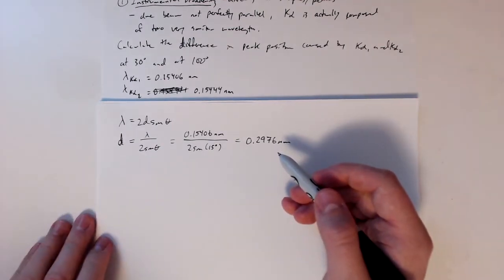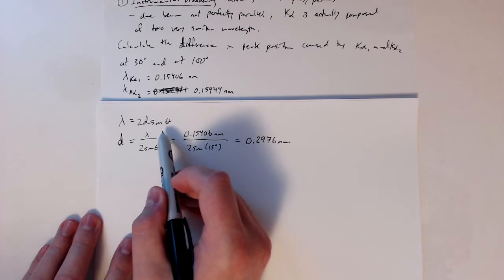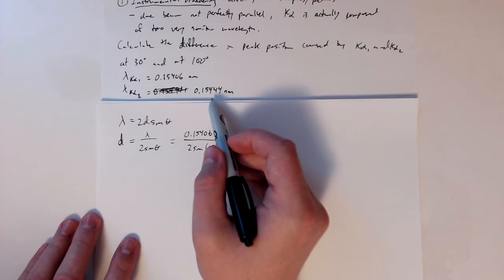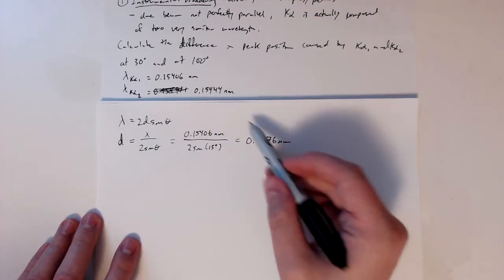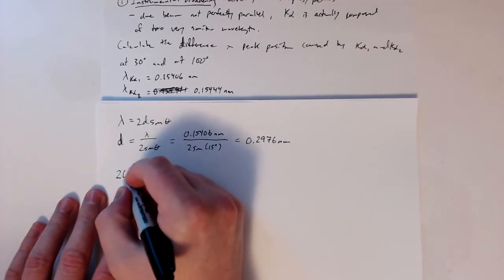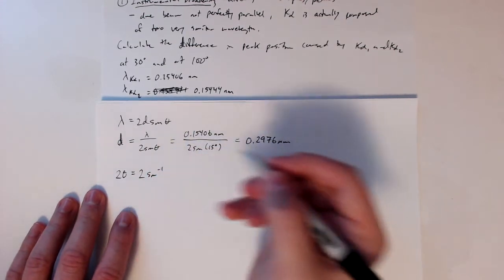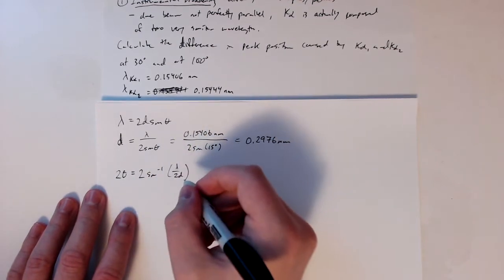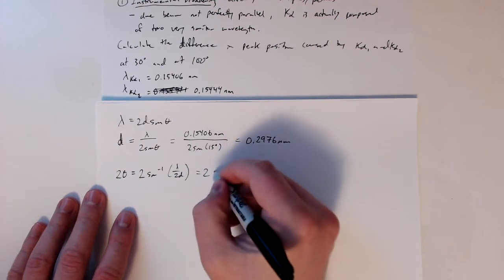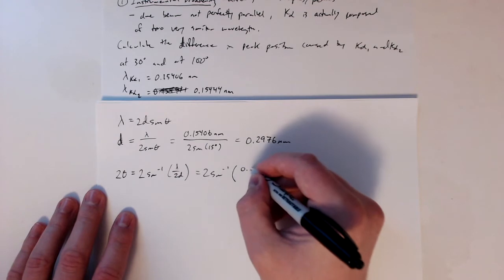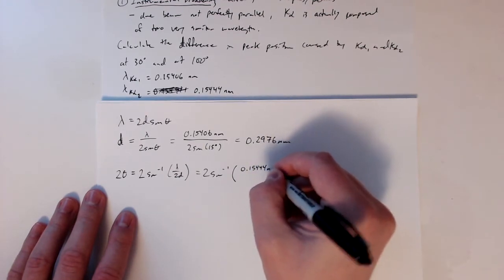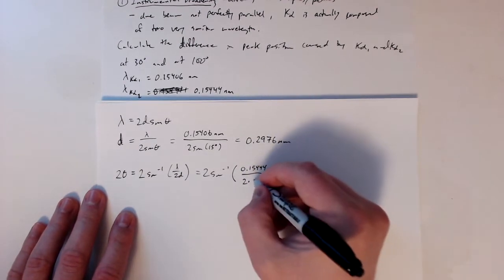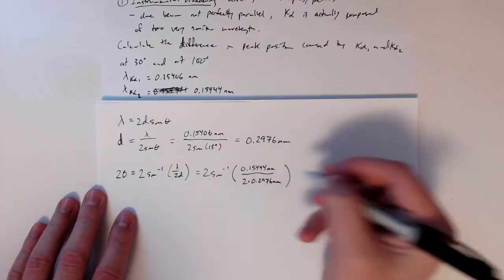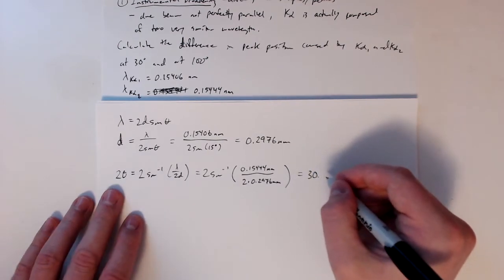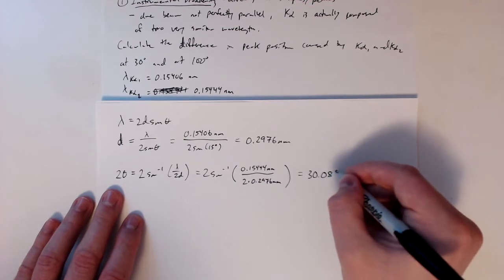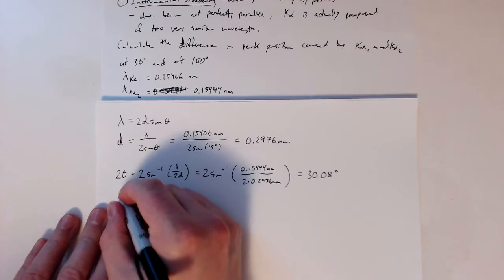The reason I did that is because now I can rearrange this and solve back for the angle using the second wavelength. Because I basically want to look at this d spacing and see the difference in the two things here. So if I solve for 2 theta, I take 2 times the sine inverse of lambda over 2d, just rearranging that expression and multiplying both sides by 2. And now I'm using the second wavelength, 0.15444 nanometers, and then my d spacing that I got up here. When I do that, I get that my angle 2 theta is 30.08 degrees.